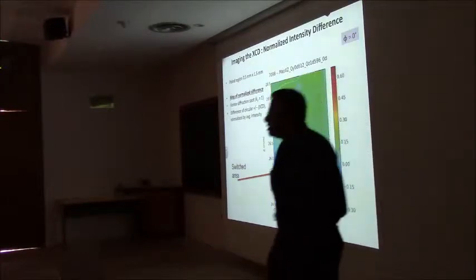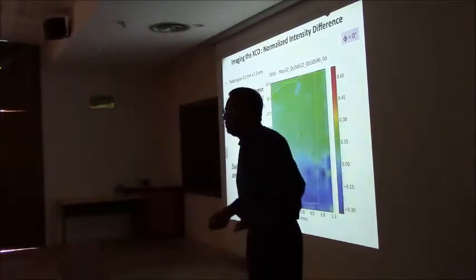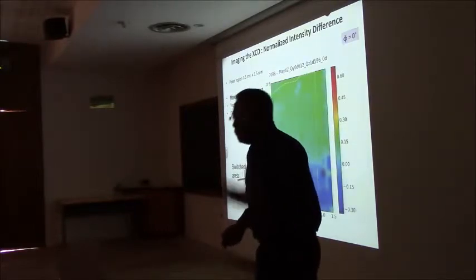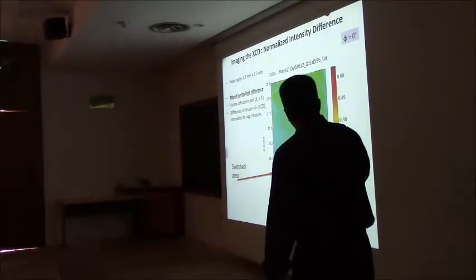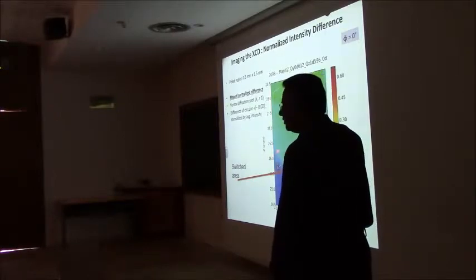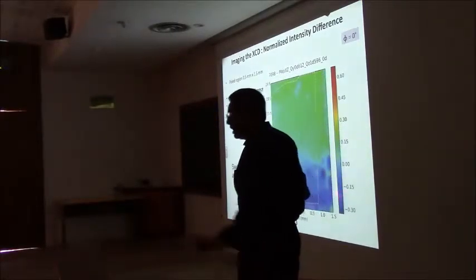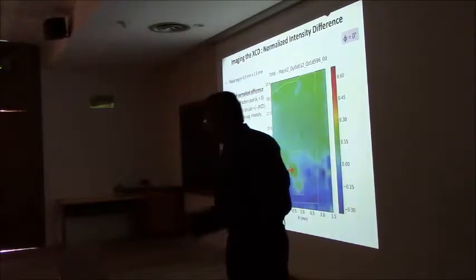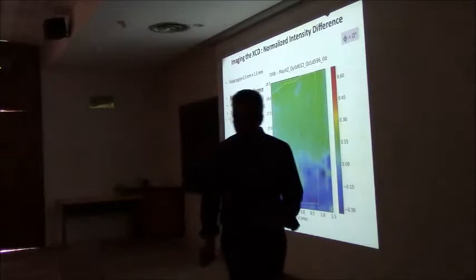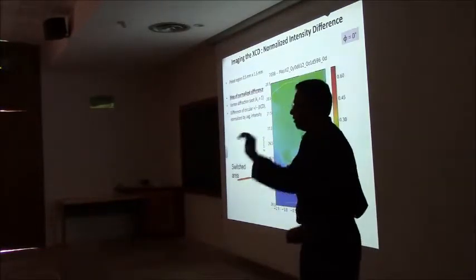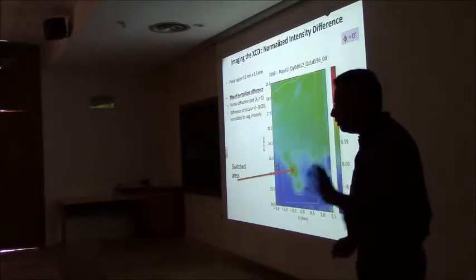Then we did an experiment which, stupidly, we did not do carefully enough. And the reason I say it's not careful is because we didn't have enough beam time. We did not do the image before the switching. So this is essentially a sample like the previous one where we had switched a portion of it. And you could see that what is positive is generally positive here, and it's negative here. A part of this has been switched from bluish, which is negative, and the circle that goes to green and to positive. So in principle, I can take something which has negative chirality and switch it to positive chirality, negative handedness to positive handedness. And we need to go back and do more quantification of this to prove that indeed that's happening.